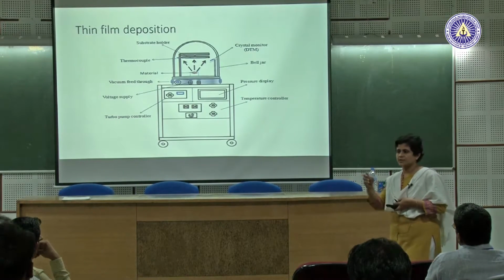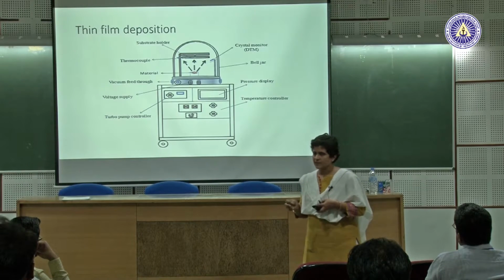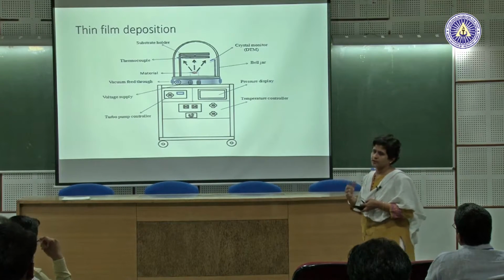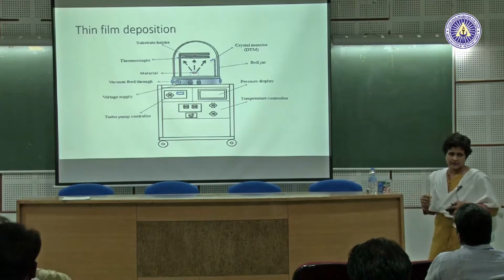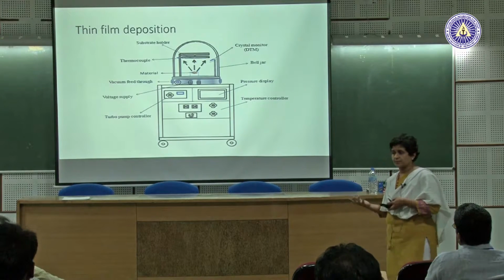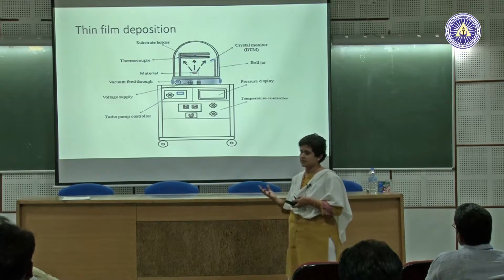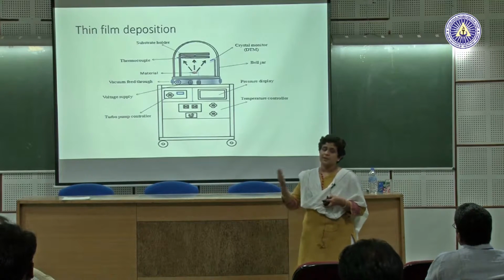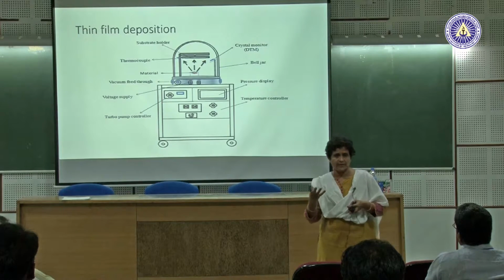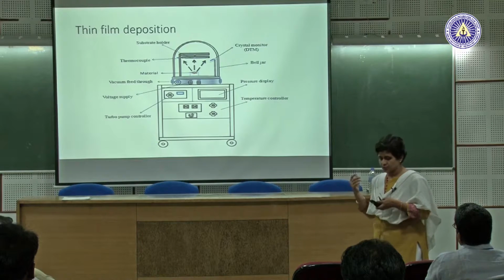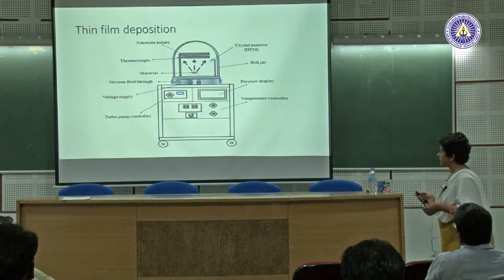And depending on how much thickness I want, I can control that, right? And as I mentioned, I don't want to get more than a few microns in this case, because then there are other problems. If you want some larger thickness, the films can peel off because of the stresses that are generated during the deposition. So there are other issues that one needs to look at if you want thicker films.